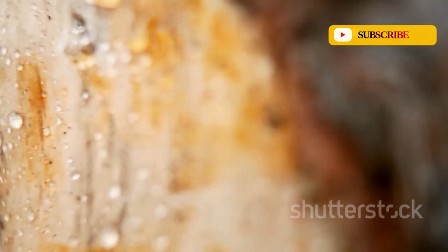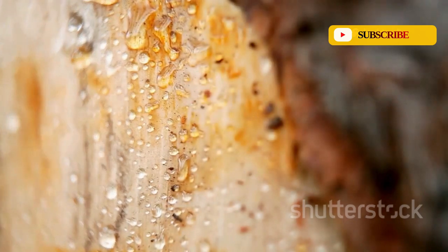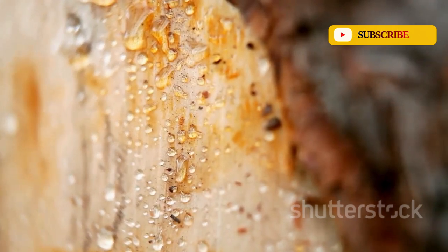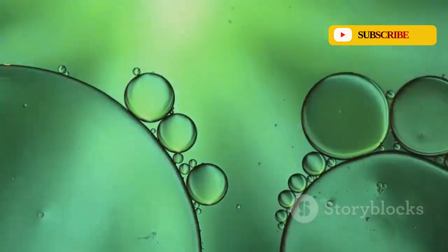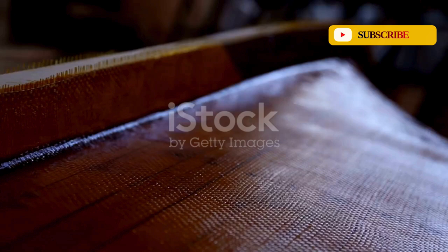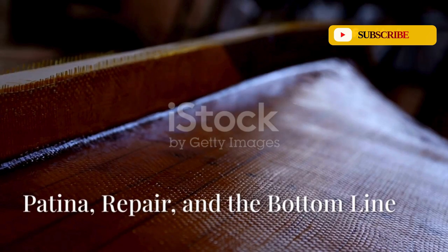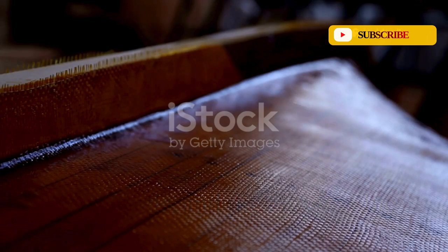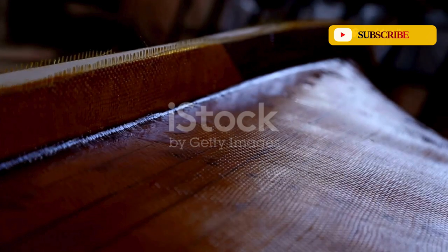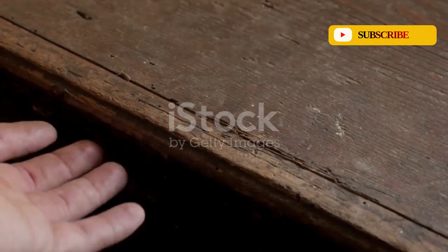Macro photos showed the water sitting proudly on top of the oiled wood, whereas on the polyurethane, you could see it start to creep under the edges of the plastic film. It's a clear demonstration of a finish that repels water versus one that merely traps it. One of the greatest virtues of an oil finish is how it ages. It doesn't fail, it gracefully wears.